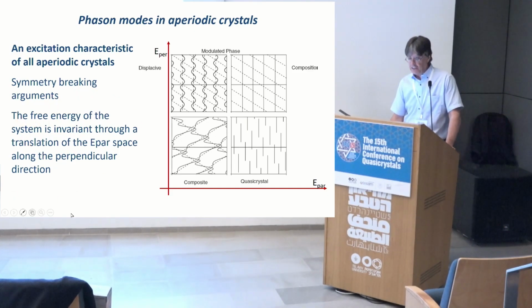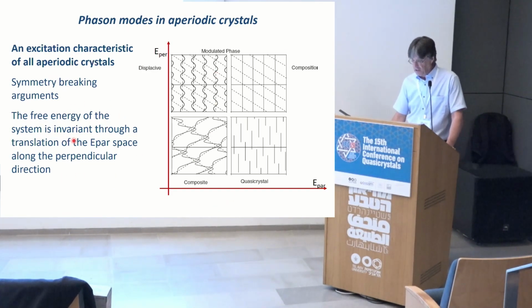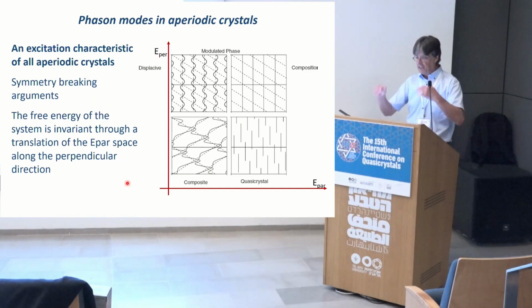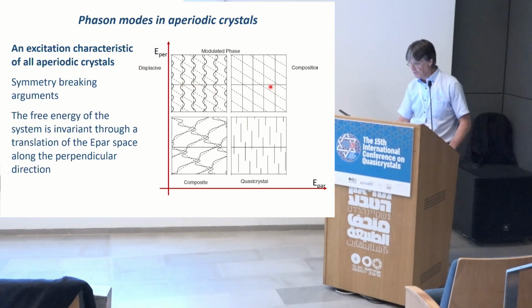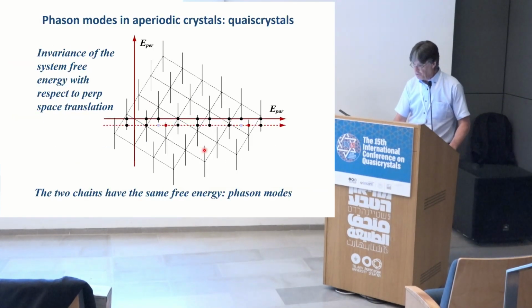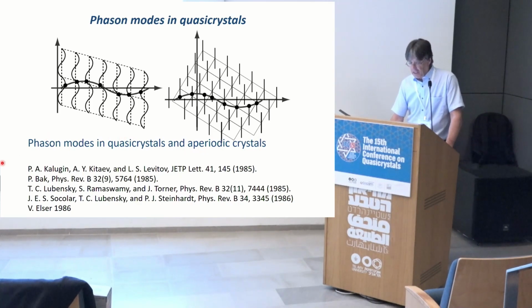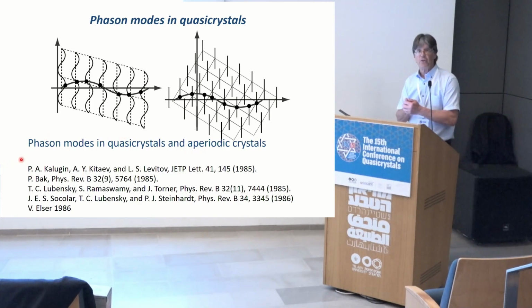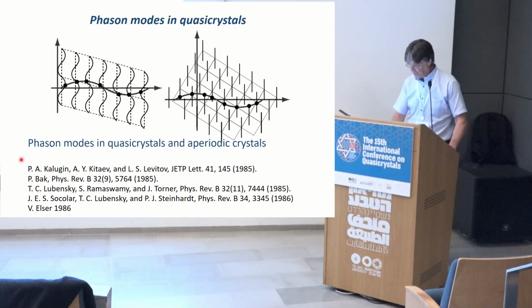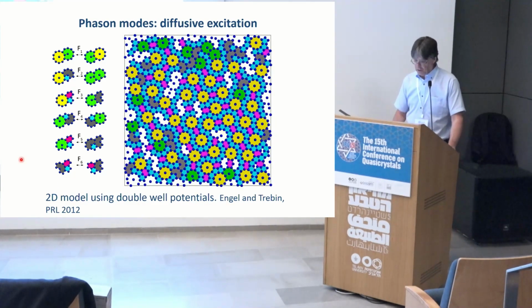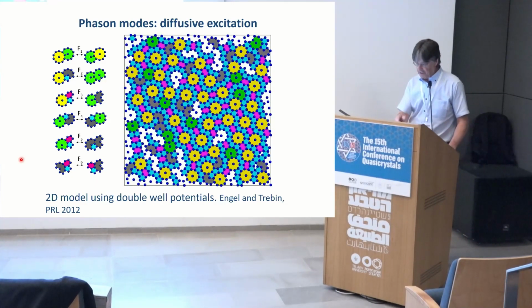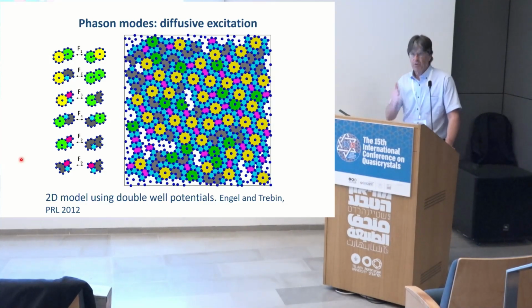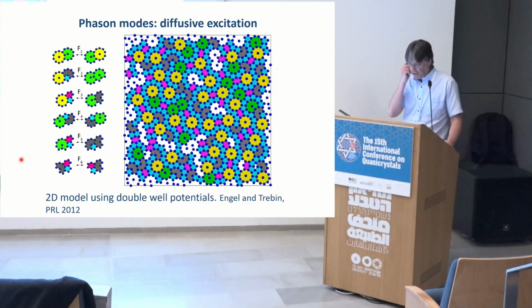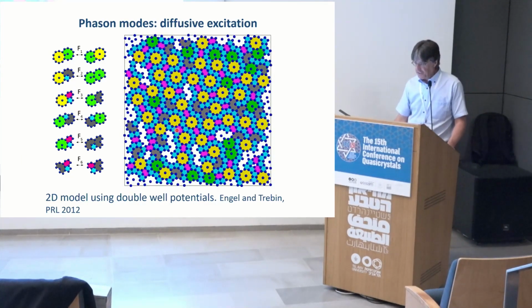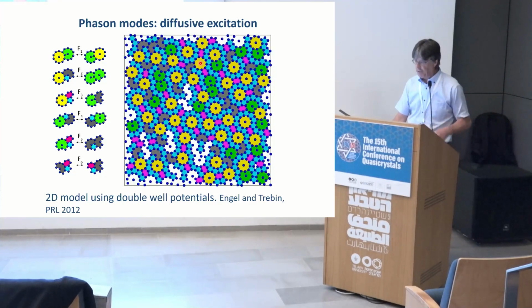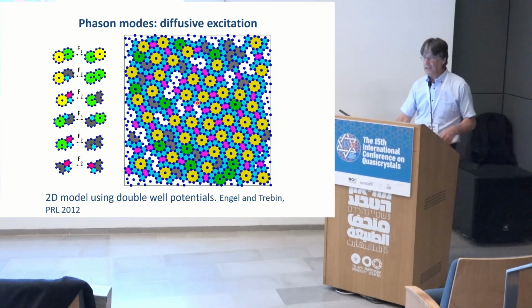And the main argument is that the free energy, if you take this high-dimensional picture, the free energy of the system is independent of the way you put the cut, this horizontal line. You can put it everywhere. So if you do that, you can derive and describe that there are phason modes in the structure, which are diffusive-type excitations. And I think the nicest way to illustrate that is taking a toy model derived by Professor Trebin, who is in the room, and Michael Engel, using a double well potential. And you see that using this double well potential and adding some temperature, there are many, many reorientations going on.